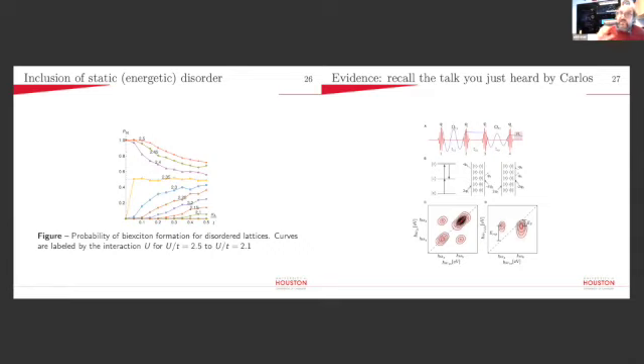What's interesting is the curves at the top, and unfortunately I can't point things out on this. You can see my hand waving around maybe. The red curve, all the way down to the yellow curve, are all the cases that would correspond to energetically bound biexcitons, where we really do have this attractive potential, this U term, kicking in to force the two excitons to be right next to each other. There's a threshold point where this value is around 2.35 for this system, where you no longer can form energetically bound biexcitons due to this interaction. However, because you're dealing with a disordered lattice, you might just fortuitously find two A and B sites that have been both pushed down and pushed up that form a little attractive well, and you can localize there.